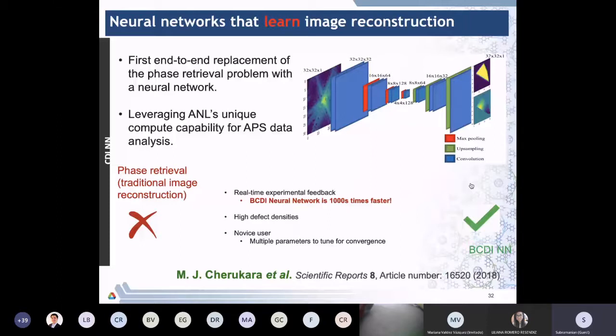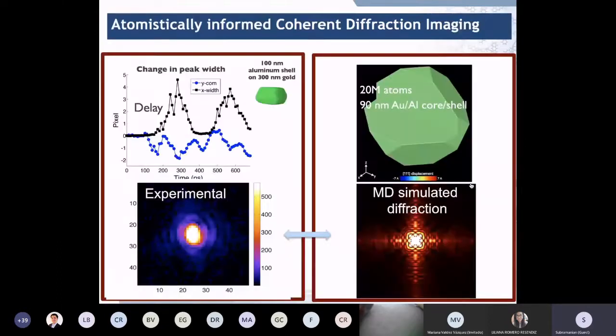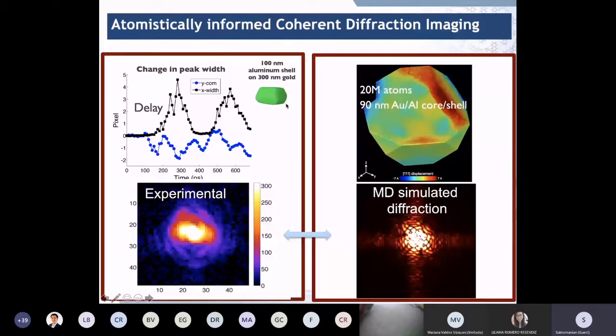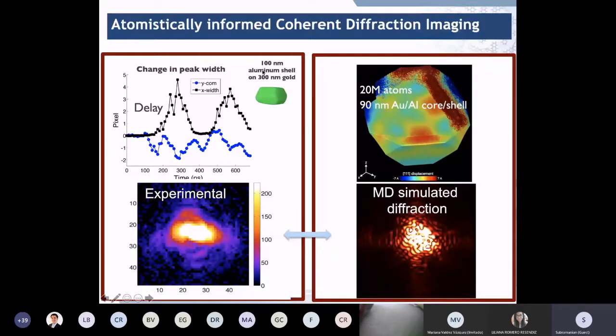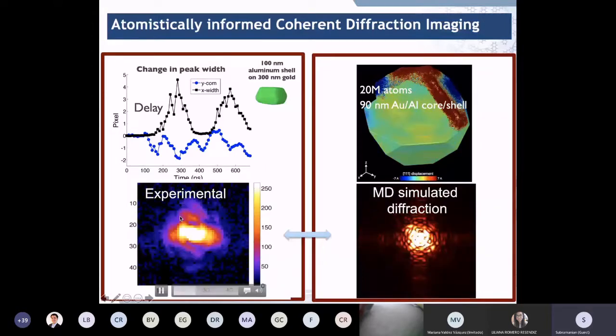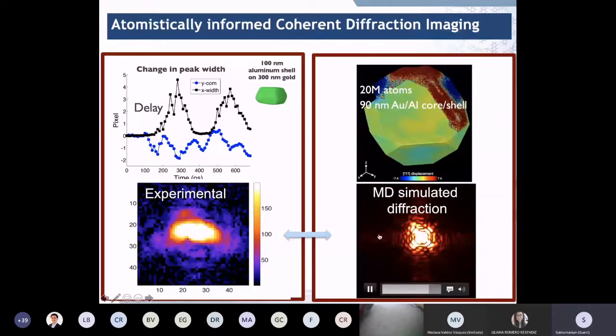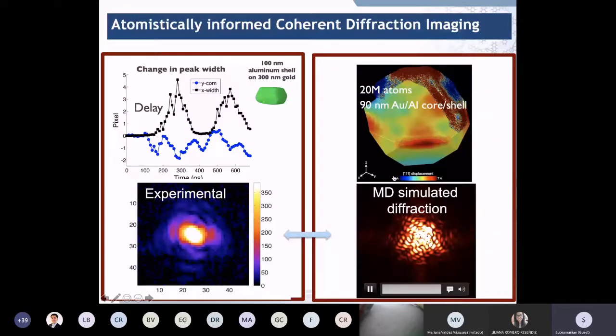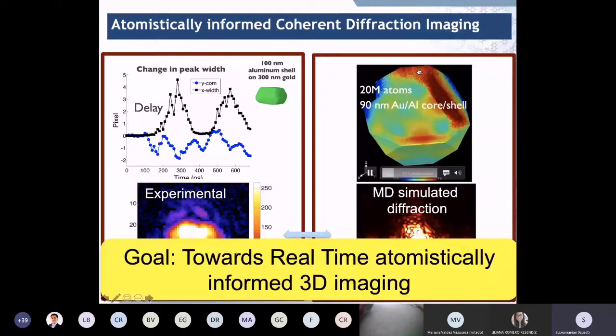You can actually generate diffraction patterns from MD, and by training a neural network to replace this phase retrieval algorithm, what one can do is, when you have an experiment where you are heating a core shell nanoparticle with a laser and you're measuring this diffraction pattern, you can compare that with a pre-computed MD simulated diffraction pattern database, and then figure out in real time how the shockwave propagation is happening. And so you can go from experimental data to directly visualizing it in real time.